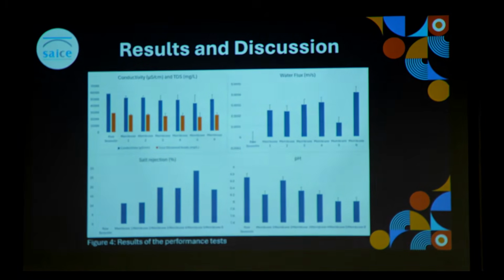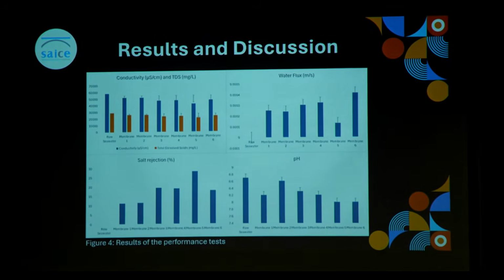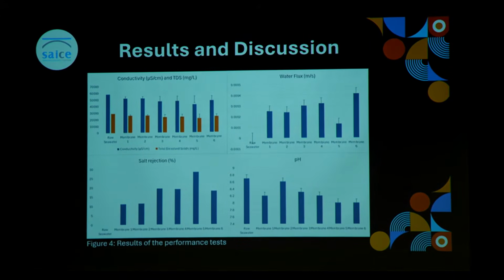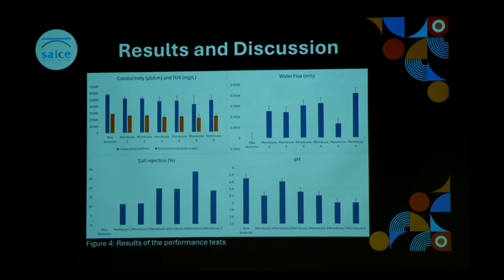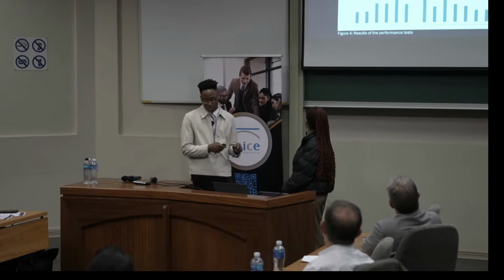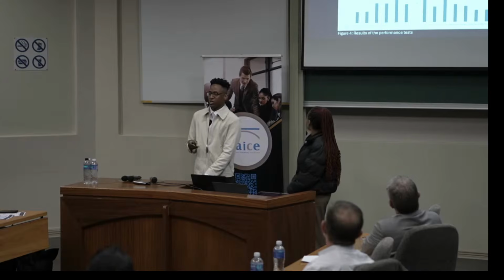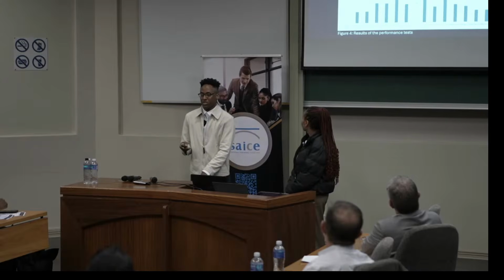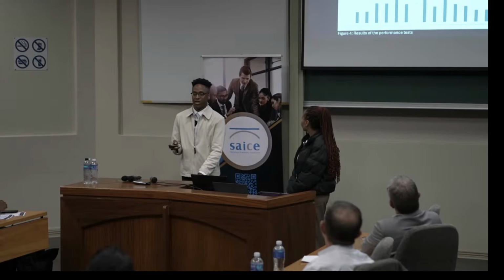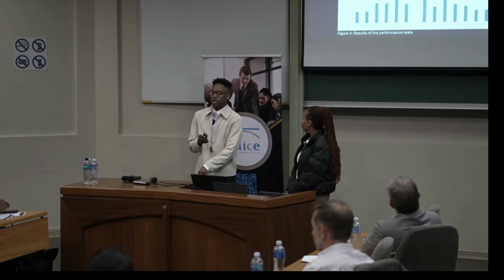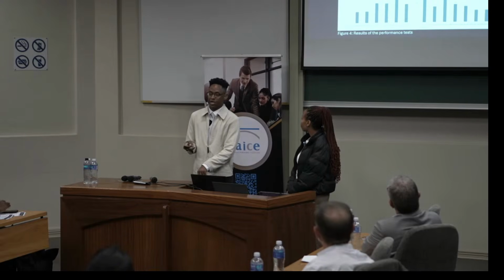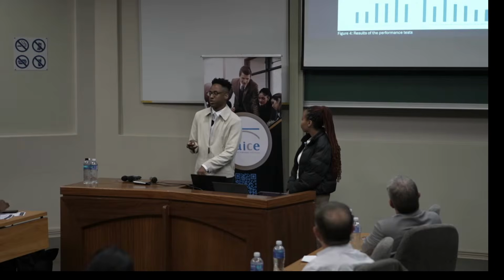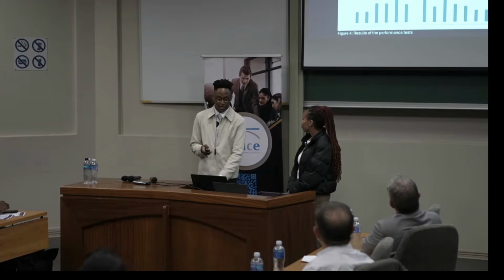Moving on to the results of our performance tests, it is important to note that the seawater that we used was completely raw, with no pre-treatment being done. This explains the relatively high values of total dissolved solids and conductivity levels that we observed. It should also be noted that salt rejection and water flux are calculated permeate properties. As a result, raw seawater does not have these values. Despite all of this, these results still remain highly reliable as they provide a clear and consistent basis for comparing the performance of each of our membranes.